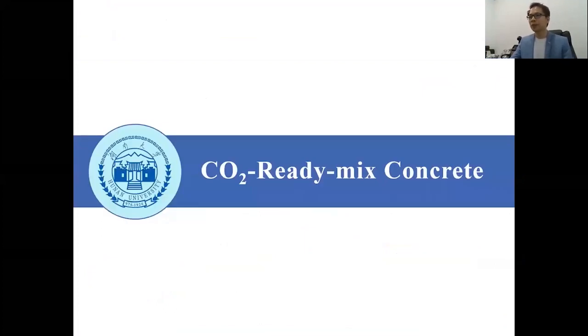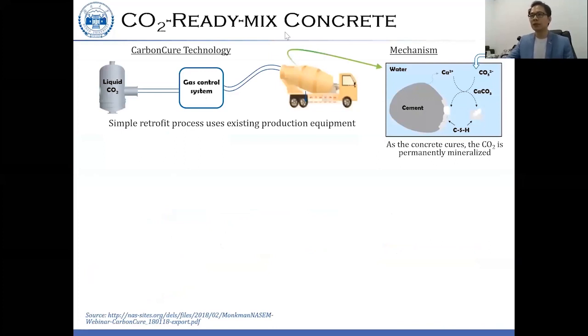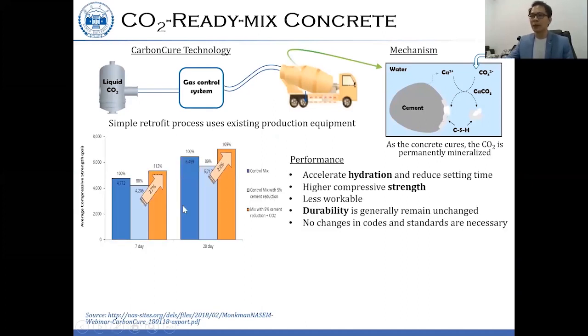So one slide for the CO2 ready-mix concrete. This technology has been developed by CarbonCure Technology, a simple retrofit process, and it can use existing production equipment. So CO2 is injected into the concrete truck, and once the cement is mixed with water, it can dissolve and release the calcium ion to react with CO2 to form nano calcite. And the result found that they can use 5% less cement under the CO2 curing. It could also provide 12% higher strength than the control sample.